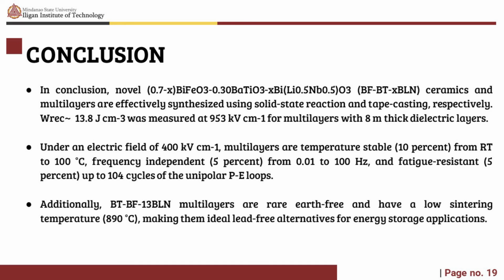In conclusion, novel BiFeO3-BaTiO3-BiLiNbO3, BF-BT-xBLN ceramics and multilayers are effectively synthesized using solid-state reaction and tape casting. A WREC of 13.8 joules per cubic centimeter was measured at 953 kV per centimeter for multilayers with 8 micrometer thick dielectric layers.